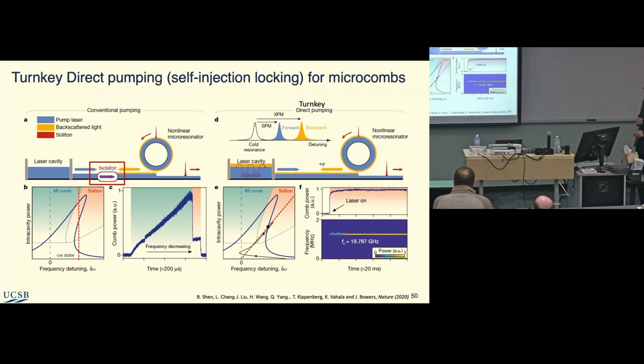So you have to typically tune the power and tune the frequency just right so as to get it into the single soliton mode. It's kind of painful, it takes a PhD. But if you do this direct pumping, we call it turnkey generation of solitons, there's no isolator. We can't integrate it with an isolator, so we had to go that way. But it turns out the backscatter from this resonator locks the laser, self-injection locks the laser to this ring.